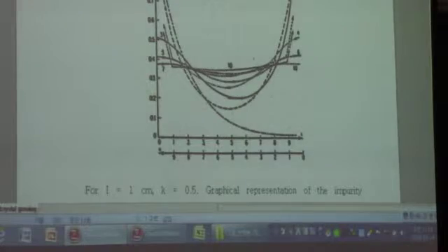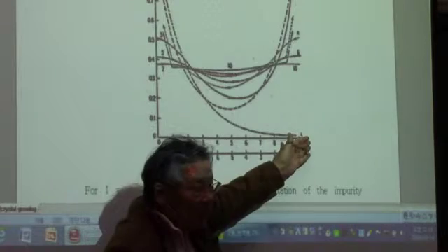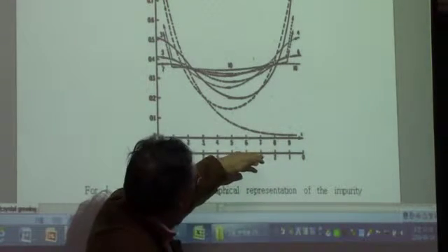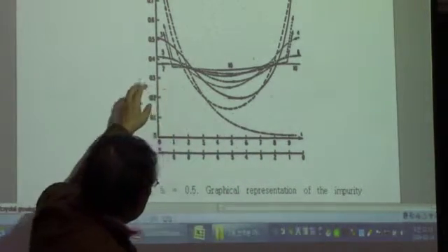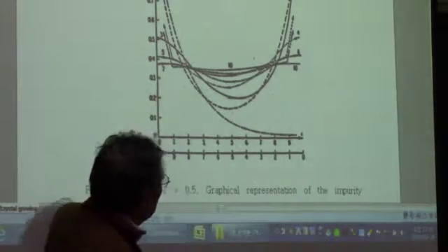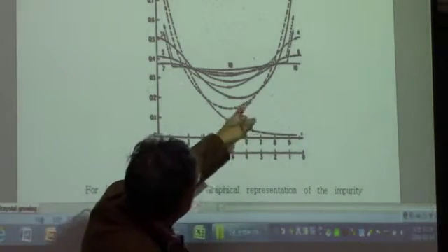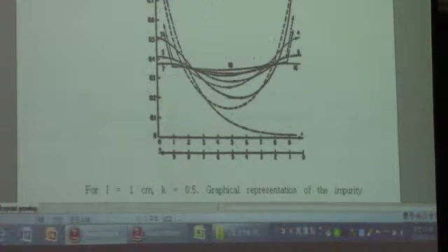After one pass, you have this much difference along the length of the rod as a dopant distribution, and then you move to the opposite direction, and that is number 2. You can see the number 2 there. Okay, and then number 3, number 4, number 5, number 6, and the opposite directions again, and then you can see at number 10, almost a flat distribution of the dopants. Okay.